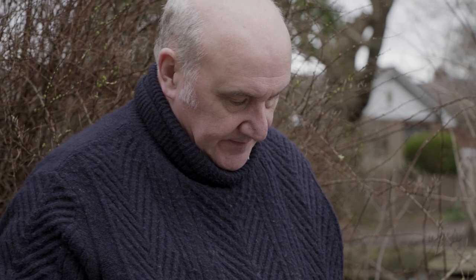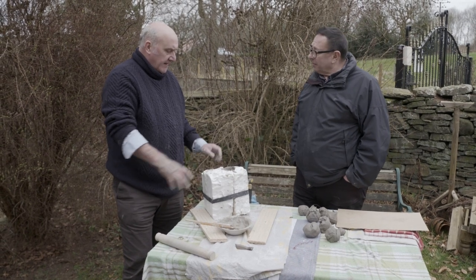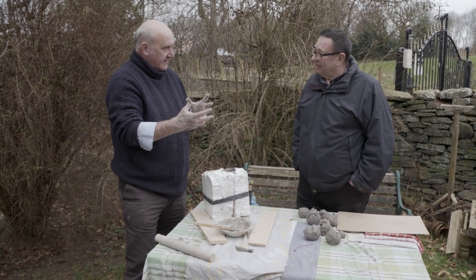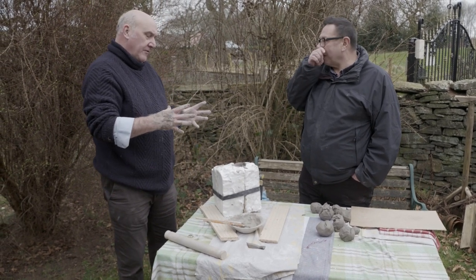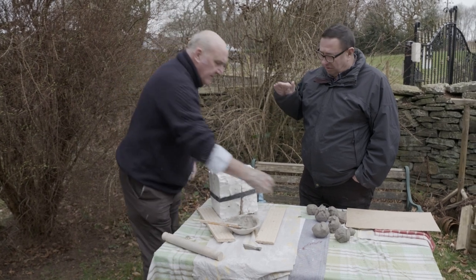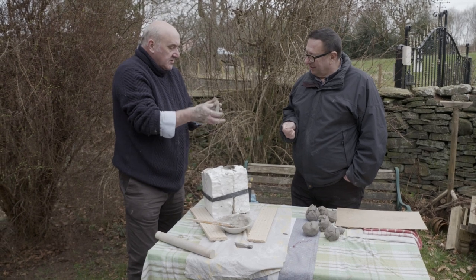So what's next? It's about two hours — we've got to get the moisture sucked out of the clay by the plaster, and that'll harden the clay up and it'll also shrink slightly, so it'll pull away from the mold. When we take it apart we'll have a hollow head ready for attaching the handle, ready for the kiln for firing. It'll be very slightly smaller once dry — just enough to pull away from the plaster mold. You have to calculate that right at the beginning. The clay comes out what they call leather hard — firm rather than just soft plastic — so you can handle it.